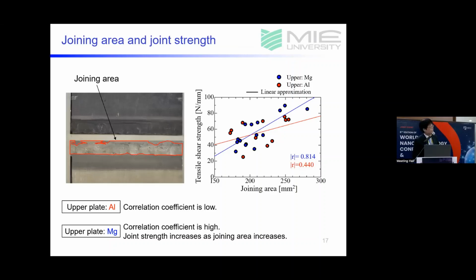The left-hand side shows the fracture surface of the joint after the tensile shear test. The area surrounded by the red line was measured as the joining area. The graph on the right shows the relationship between the joining area and the tensile shear strength.